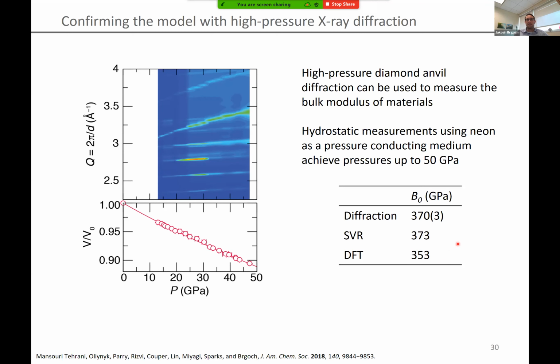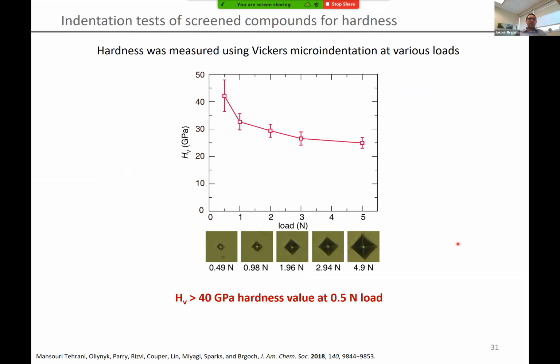So overall, excellent agreement. Looking at the material's Vickers hardness, well, this is exactly what we had hoped. You can see that at low load, we are sitting right at the 40 gigapascal superhard threshold. As you increase the load applied to the material, you can see the hardness decreases. Again, this is the load, the indentation response curve.